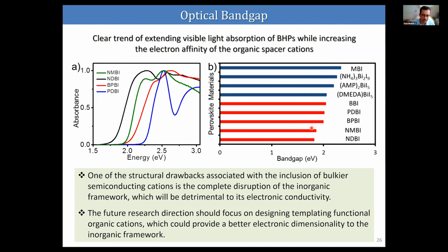And of course, there is a drawback of including bulkier semiconducting cations in the structure of bismuth material, because it can completely destroy the inorganic framework. So the future research direction should be focused on designing templating functional organic cations. So they should be able to template the inorganic octahedra packing, which could provide better electronic dimensionality to the inorganic framework.